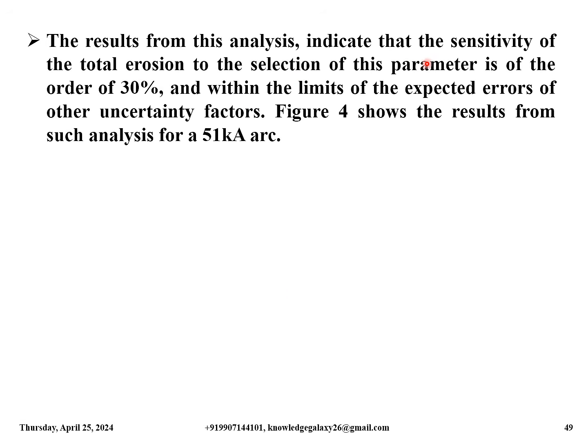The results from this analysis indicate that the sensitivity of the total erosion to the selection of this parameter is of the order of 30% and within the limits of the expected errors of other uncertainty factors. The figure shows the results from such analysis for a 51 kA arc.